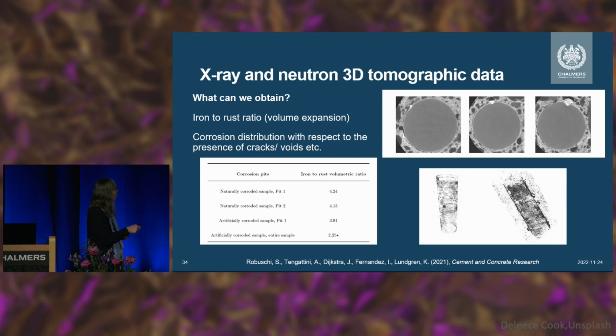And from the 3D, I mean, now you are showing it in 2D, but you have to imagine that this is actually a 3D scan, we could calculate the volume of the corrosion products. And we could, of course, also calculate the volume of the steel that was lost. And from that, we could estimate the volume expansion. I don't know if you see the numbers, but for the naturally corroded samples, it was around 4. For the artificially corroded sample, we managed to find one such corrosion pit with one such void, and estimated slightly less, 3.9. It's roughly the same.